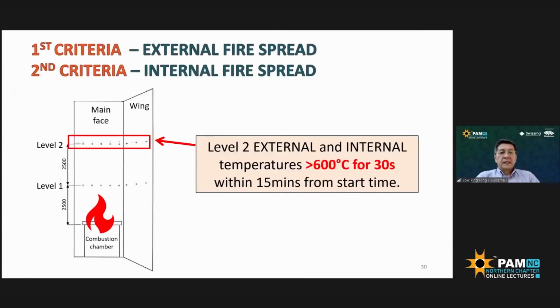Now, the test results. The first two criteria, as explained by Suok Ling, are about the temperature reading at level two. They planted a thermocouple at the external surface of this drywall, they planted one in the cavity, and they also planted one inside the drywall system. All these criteria are to measure the fire spread, and the way they measure this is by taking the temperature reading at level two within 15 minutes from start time.